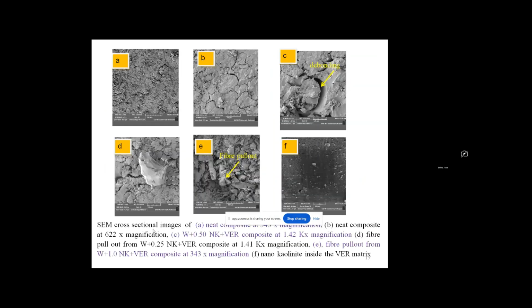This is the SEM images. You can see in A, B, C, this is the surface fracture morphology. You can see in C, there is debonding observed, debonding of the fiber with the matrix. And in D and E, it shows the fiber pullout during the mechanical stretching. And F shows the tiny nanoparticles scattered inside the matrix.